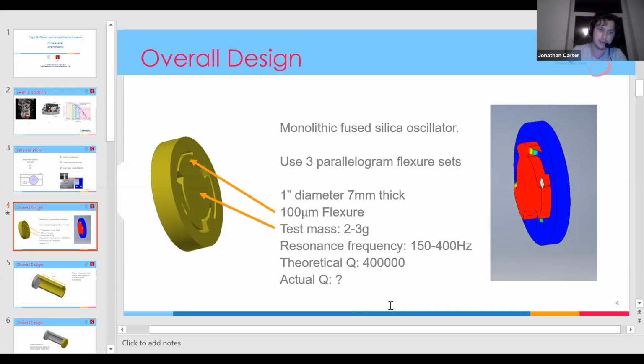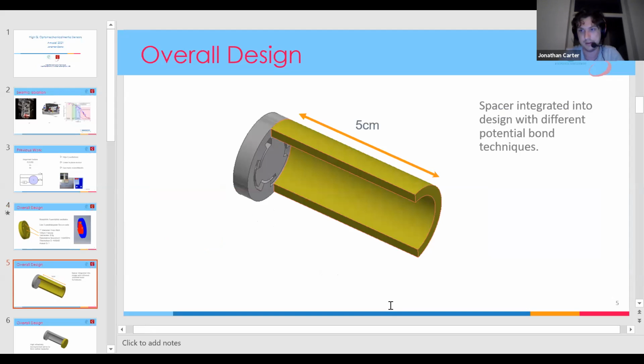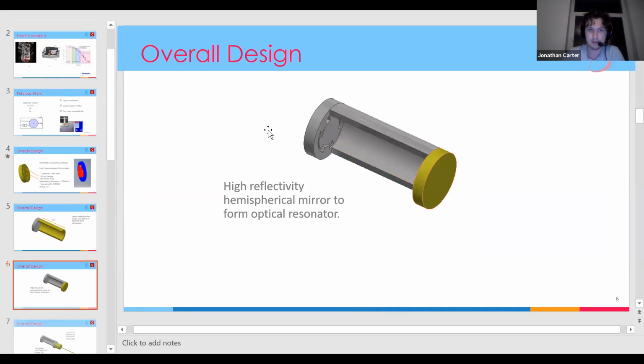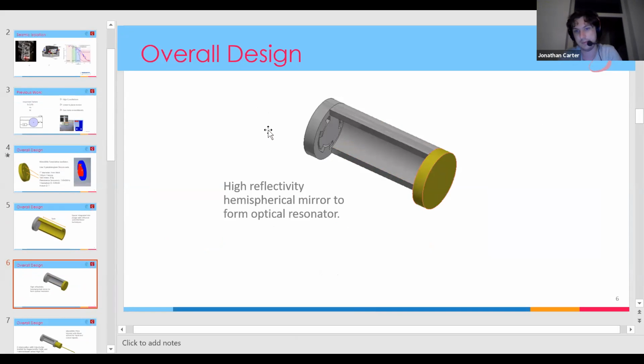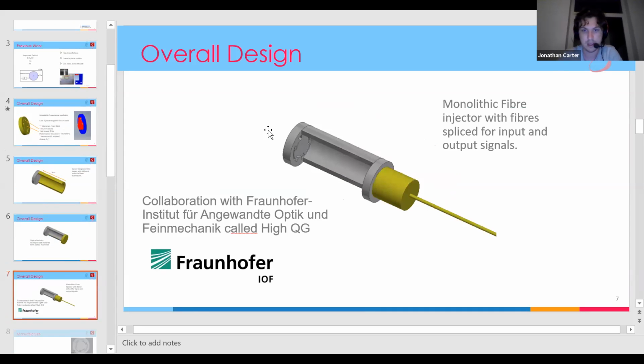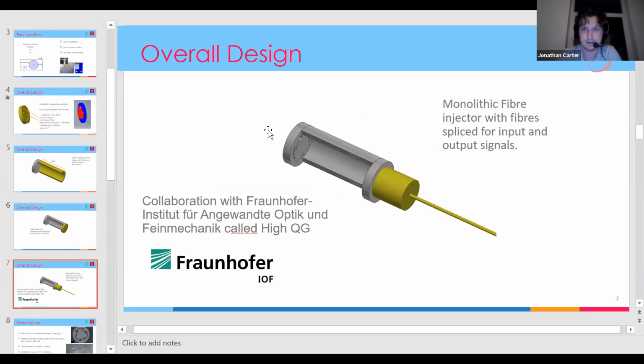So the idea was to take this design and integrate it with just a 5 centimeter long spacer, so that the design fits about yay big in your hand. And we had a few different bonding techniques that we would try to bond this spacer to the rim of the outer oscillator. We could then integrate a highly reflective hemispherical mirror to form an optical resonator. This would allow us a very precise measurement of the test mass readout, so that we are truly limited by thermal noise. The overall final design had some ideas for combining a monolithic fiber injector with this, which could directly inject and take out the beam. But I won't be talking too much about that today because that's currently a far distant future project.